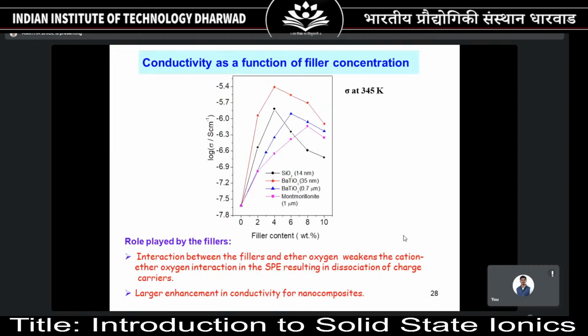If you look at the conductivity as a function of filler concentration, because our aim is to optimize any property whenever you add reinforcement material in the matrix. Filler content changes from 0 to 10 weight percent, and the conductivity enhancement. This is my host polymer electrolyte or pristine polymer electrolyte. You kept on adding weight percent of the fillers. Here I am using other fillers as well: silica, barium titanate of 2 different particle sizes, and montmorillonite, a mixture of several oxides.